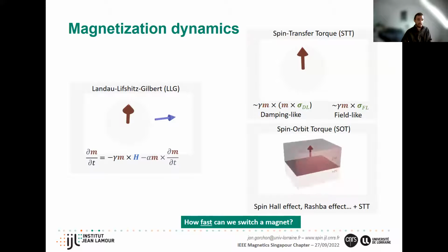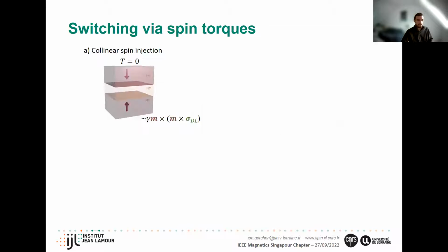And so the question is, how fast can we actually switch a magnet? Let's take a typical example that's been studied very largely in the literature, which is the spin valve. You have two ferromagnets separated by a non-magnetic layer. If you start in the collinear configuration, meaning you have the two ferromagnets anti-parallel or parallel to each other, at zero temperature you would expect no torque. You send your current, it gets polarized on one layer, and then it tries to exchange with the other layer. But because this torque is proportional to m cross sigma, you basically expect no torque.